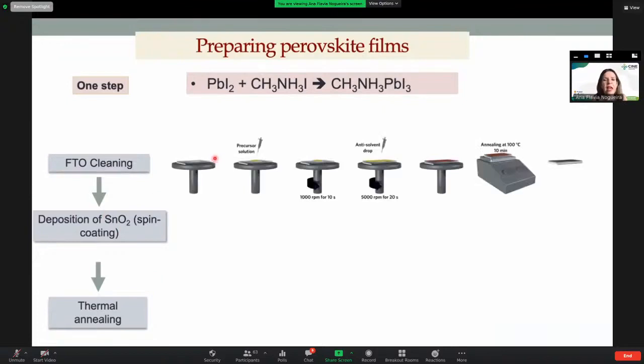And what I have is a precursor solution. In this solution, I have all of the precursors for the perovskite, in this case lead iodide and methyl ammonium iodide. So we use spin coating in order to spread the solution here. Here, another important step: just a few seconds before turning off the spin coater, I drop what we call an antisolvent. This antisolvent is going to force the crystallization of the perovskite.